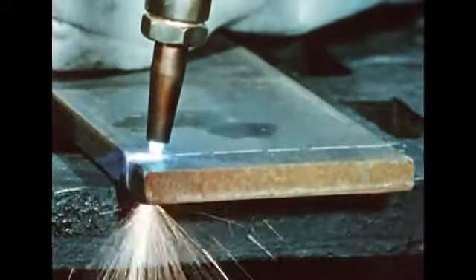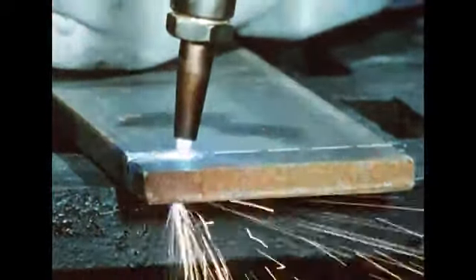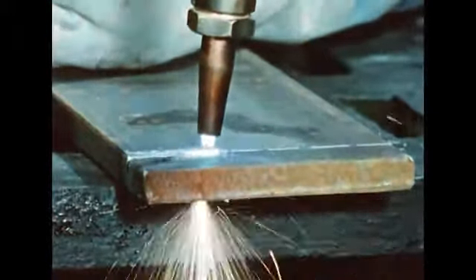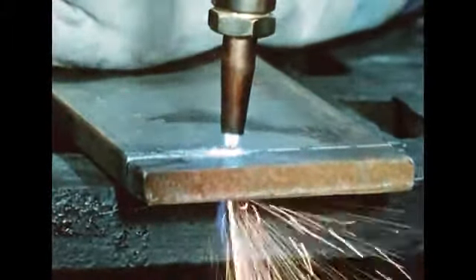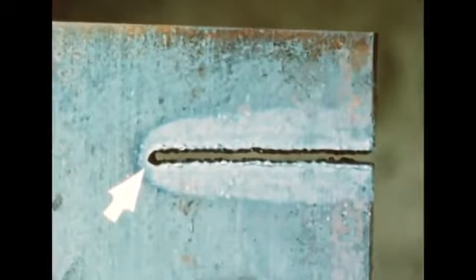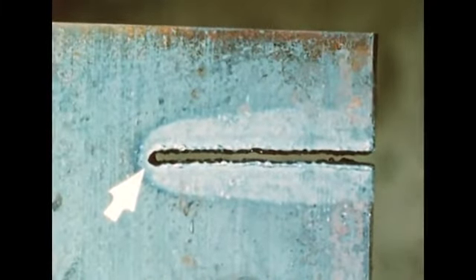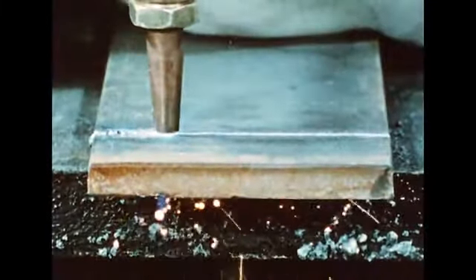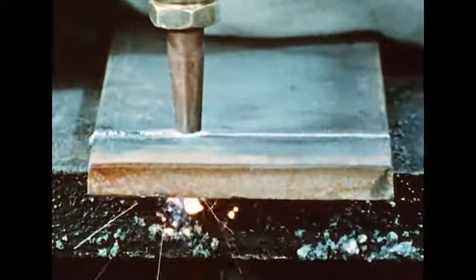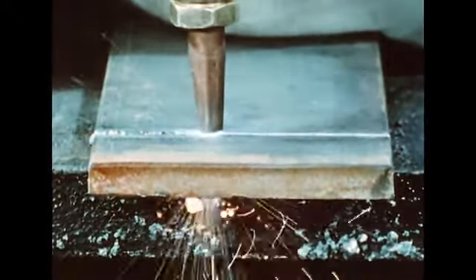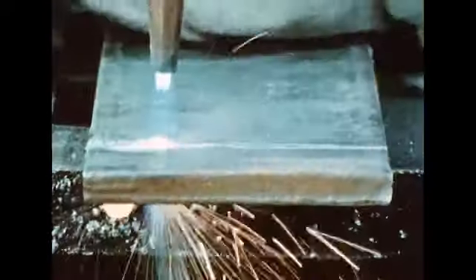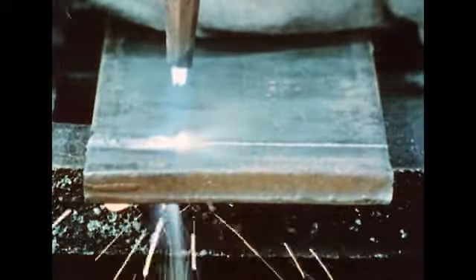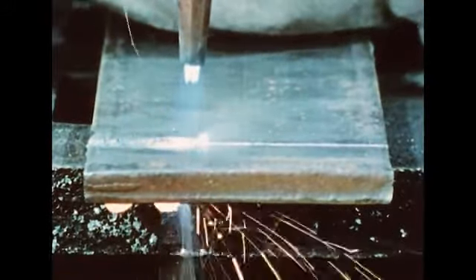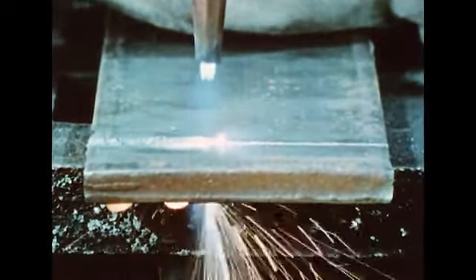Keep the end of the nozzle about 1/4 of an inch above the plate. This will result in a smooth, narrow cut. Like this. If the flames are too close, the top edges of the cut melt over. Like this. If they are too far away, the heat and oxygen stream spreads, and the cut will be too wide and ragged. Like this one.